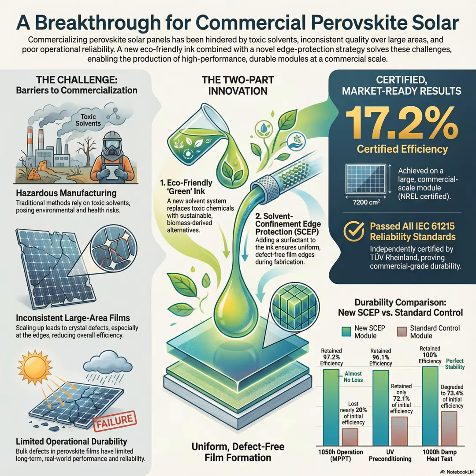Okay, so how did their SCEP module do compared to a traditional one? This is where you see the void-free film strategy pay off. The SCEP module maintained 100% of its initial efficiency after the full 1,000 hours. The control modules, for comparison, degraded badly. They plummeted down to 73.4% efficiency. 100% retention after that kind of abuse is unheard of for this tech. It directly validates the quality of the crystallization.